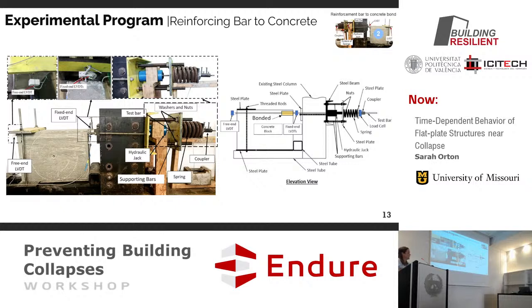And this is a better test than just taking a cylinder and pulling it straight out, because I'm not creating any compression here. The reaction's back here, and so where I'm testing the bond, I don't have any extra compressive forces. I'm just leaving that purely to the bond load. The bonded length is just a little bit in here. All this other rebar had a plastic sleeve around it, so it was not bonded. There's only about 5 to 7 inches bonded within that.